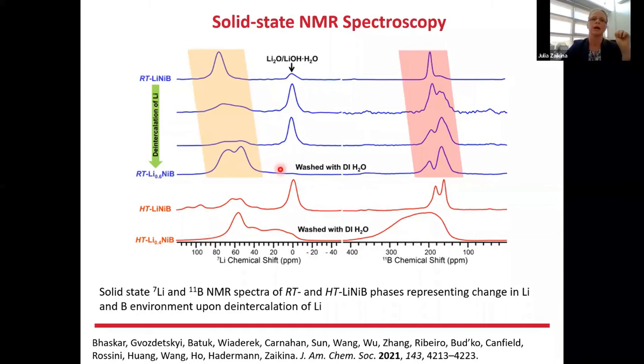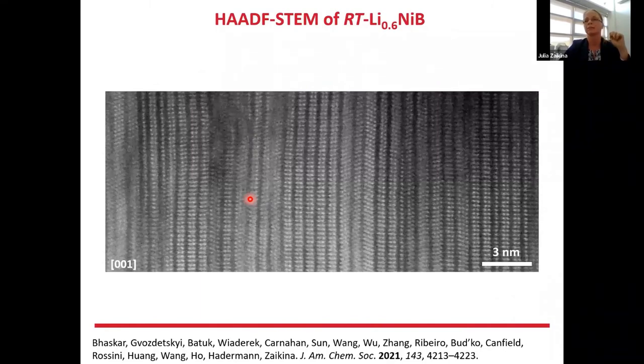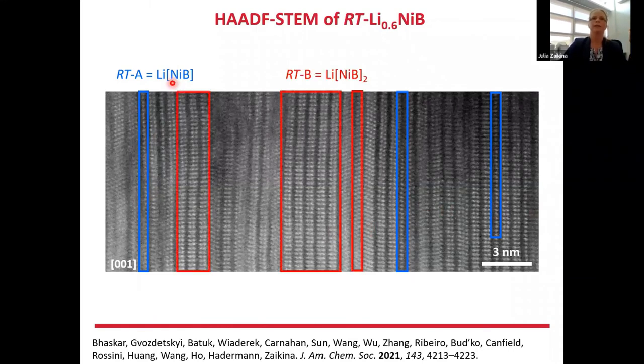But this data also suggests that our lithium is not fully deintercalated from the layered structure. So we need to use more advanced characterization methods. So we use scanning transmission electron microscopy, which allows us to see that the layered structure is still preserved. However, there were some changes the material undergoes upon the deintercalation. So we do see that fragment where one nickel-boron layer alternating with one lithium layer is still preserved in some cases, very minor cases though. However, the most abundant motif is where we have two nickel-boron layers which form this nickel boron 2 fragment, and those layers are now alternating with the lithium layer.